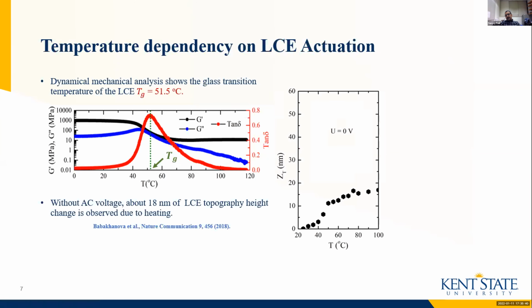We also know that liquid crystal elastomer responds to temperature. So before applying any electric field, we studied the temperature dependency of our liquid crystal elastomer coating. We saw that in the temperature range of 20 to 100 degrees Celsius, there is 18 nanometers of surface topography change, like height change of the elastomer, due to heating.